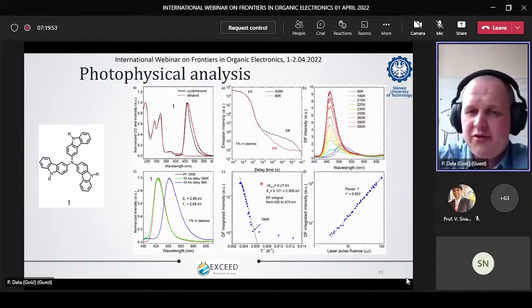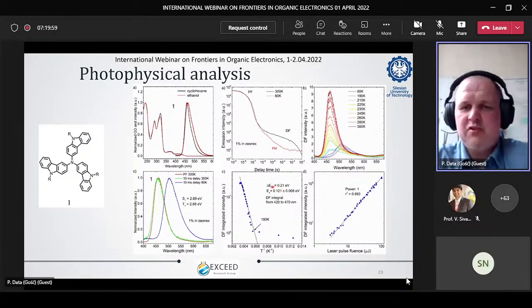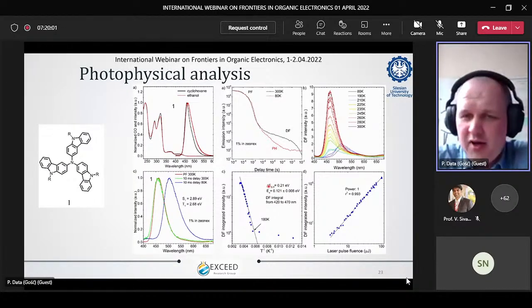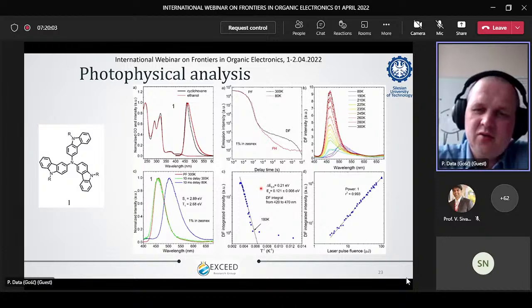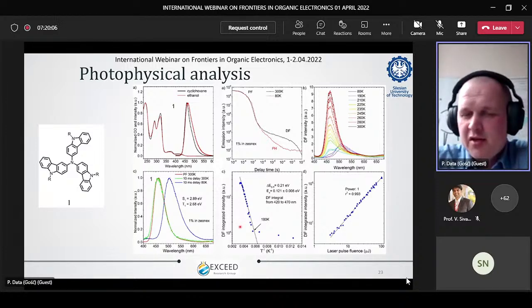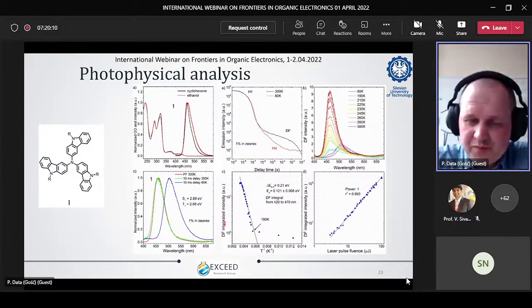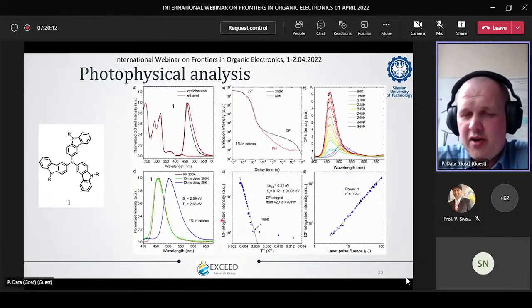Nevertheless, it's not the actual energy which you need to put into your molecule to push from the triplet to the singlet state. Actual energy is characterized in a slightly different way. We take your delayed fluorescence emission and characterize how it changes at different temperatures. So here you have an Arrhenius plot.